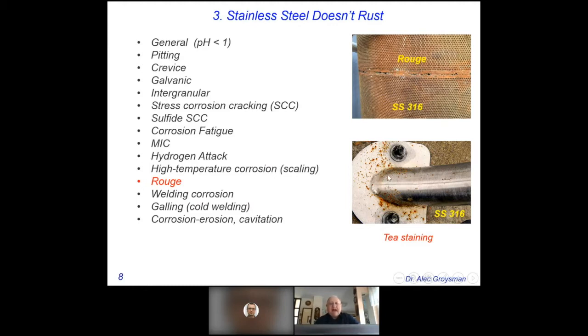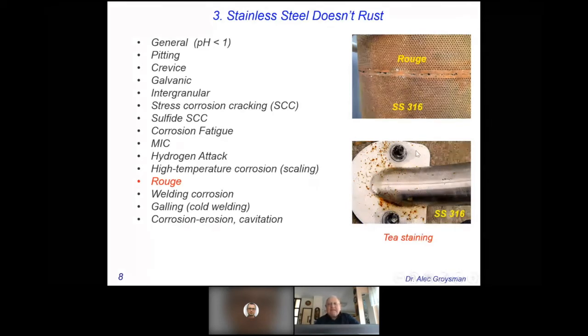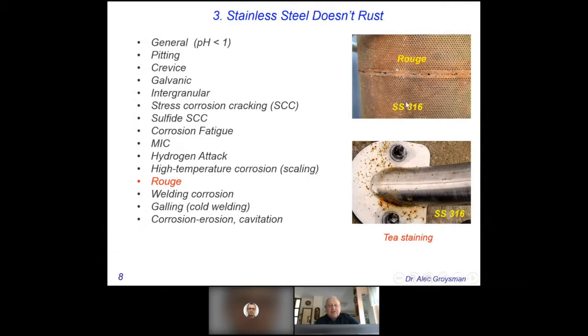In some environments, such as very close to the beach, where there is a lot of salt in the air, the passive layer may not be able to form, and some corrosion may take place. Rouge is a commonly used term for the visible corrosion product of stainless steel. It can be composed of several forms of iron oxides, with red ferric oxides being the predominant form.